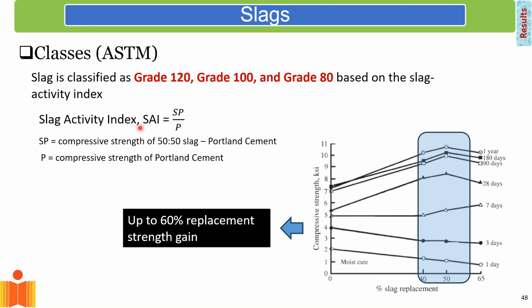And the way we get the activity index is in terms of the compressive strength of a 50-50 slag Portland blend compared to the compressive strength of ordinary Portland cement blend. And up to 60% replacement of slag, we find that we are able to regain the strength and also produce an improvement in the long-term strength compared to OPC. So slags, therefore, we can replace cements or clinker by almost 70%.